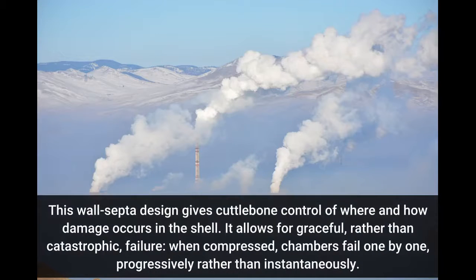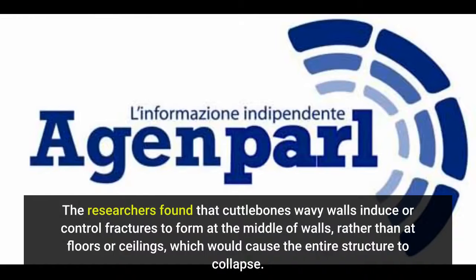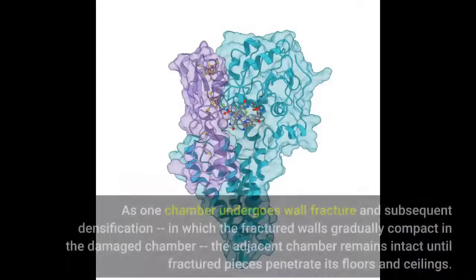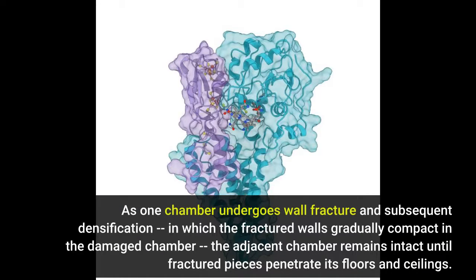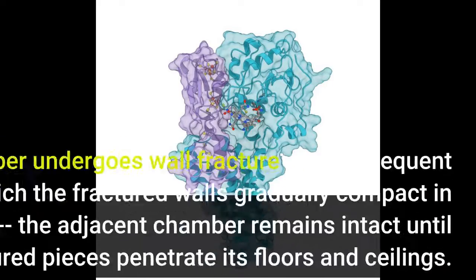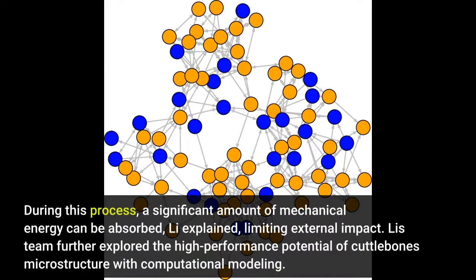This wall septa design gives Cuttlebone control of where and how damage occurs in the shell. It allows for graceful, rather than catastrophic, failure. When compressed, chambers fail one by one, progressively rather than instantaneously. The researchers found that Cuttlebone's wavy walls induce or control fractures to form at the middle of walls, rather than at floors or ceilings, which would cause the entire structure to collapse. As one chamber undergoes wall fracture and subsequent densification, in which the fractured walls gradually compact in the damaged chamber, the adjacent chamber remains intact until fractured pieces penetrate its floors and ceilings. During this process, a significant amount of mechanical energy can be absorbed, Li explained, limiting external impact.